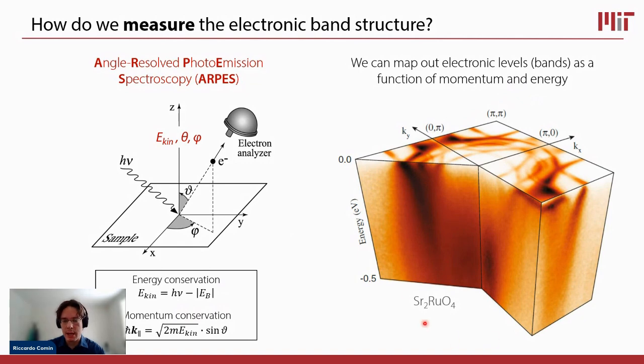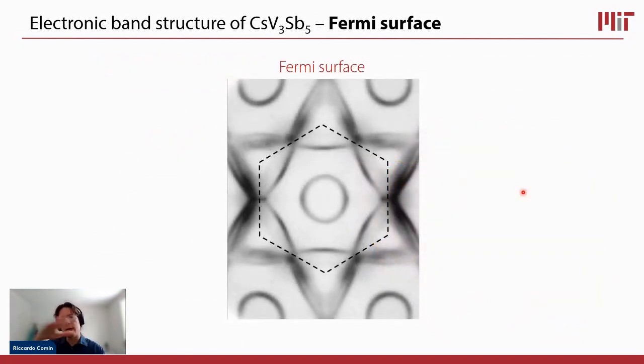And this is here as a 3D volume plot of what this looks like in a particular material, strontium ruthenate, where you see the electronic bands as a function of energy, but also you see their shape as a function of momentum. So if you now look at how things look at the Fermi energy, so we look at the Fermi surface, or where the bands are at 0 energy, we see that there are different bands as expected.